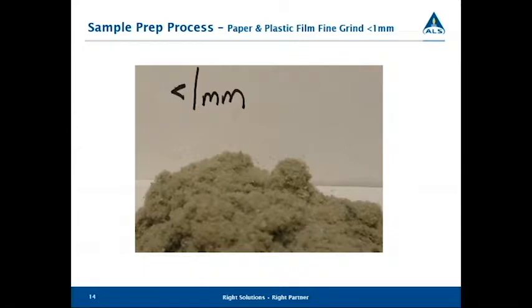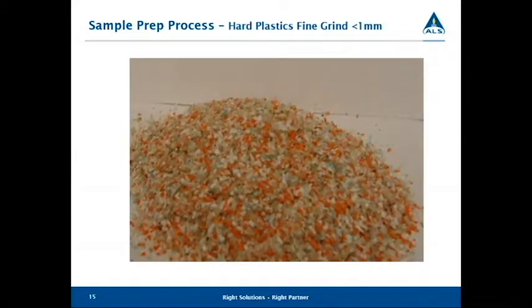So here's a picture of, this is primarily that paper, but there's a lot of plastic film in there, and you can see how finely that's ground. Even though it's ground fine, you can still see that there's some heterogeneity in the sample. Here's a plastic sample, all hard plastics, that was ground down to 1 millimeter. And you can see, again, the heterogeneity of the sample.